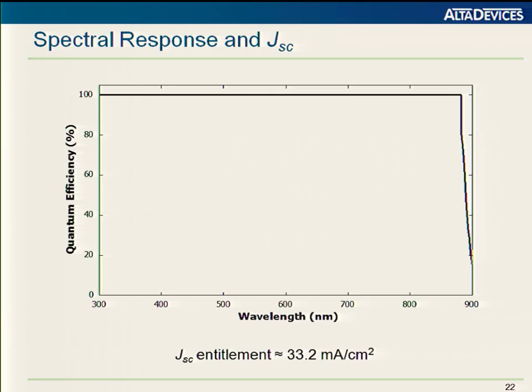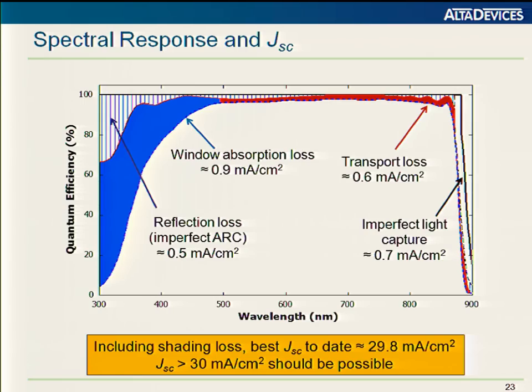If you look simply at the band gap of gallium arsenide, in a best case scenario, you might achieve beyond 33 milliamps per centimeter squared. In our cell, there are various losses. Some are unavoidable, some may be avoidable. We have a shading loss due to the front metallization. Even at a one-sun device, you can't reduce this to zero. We have an anti-reflection coating that's not perfect. It's designed to maximize absorption in the useful part of the spectrum, but has some loss associated with it.